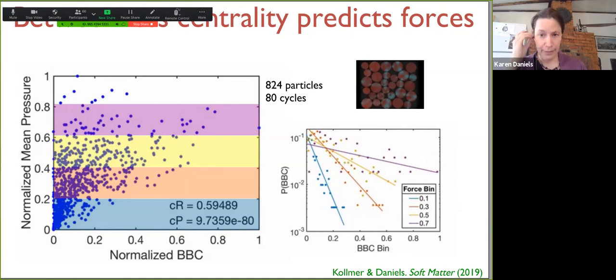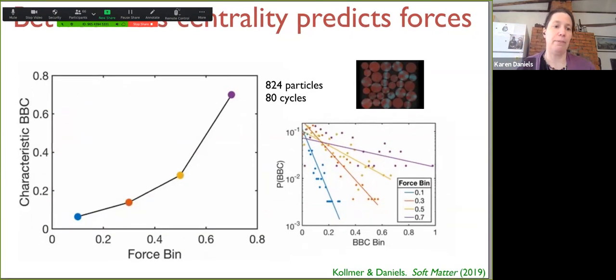These look quite different from each other. They're approximately exponential, so they're well characterized by a mean. If I plot what that characteristic betweenness value was, the slope on a log plot, versus which force bin, you can see that the higher the betweenness of the particle, the more likely it is to be in a high force bin. There is randomness in this process. Every time we generate the network, it's slightly different. But there is a trend: if you are on many paths, then you're more likely to end up with lots of force.